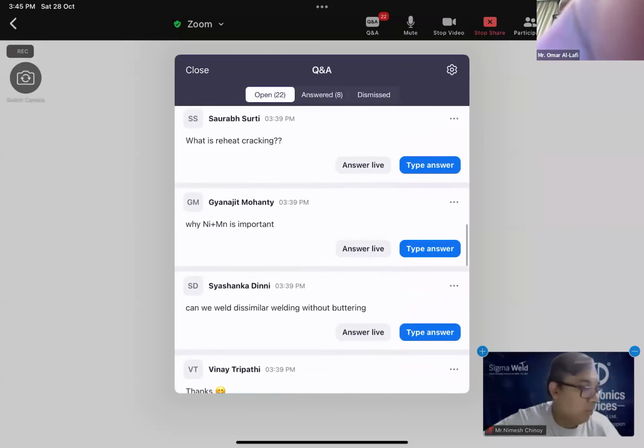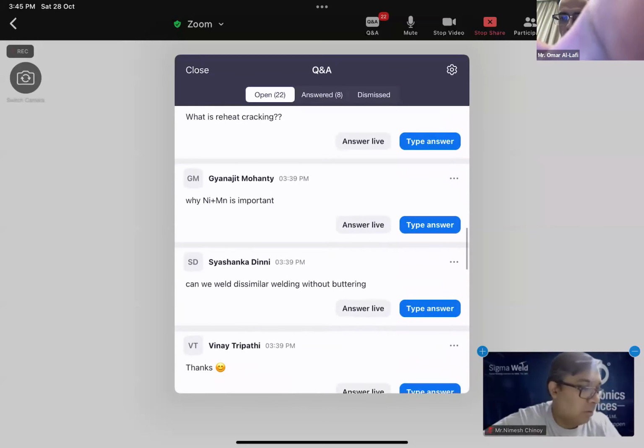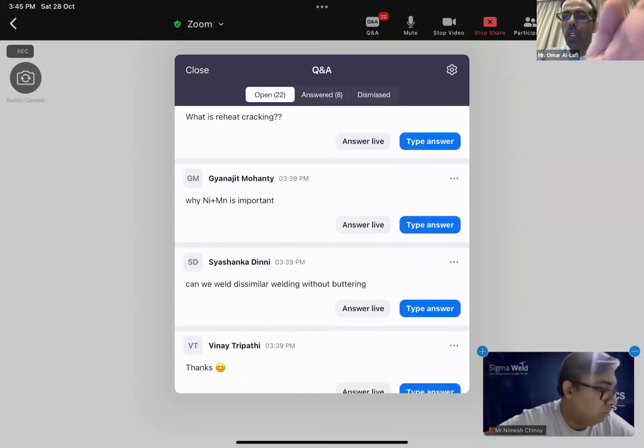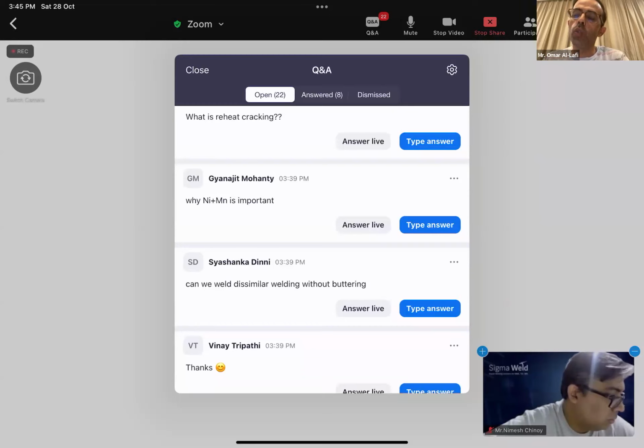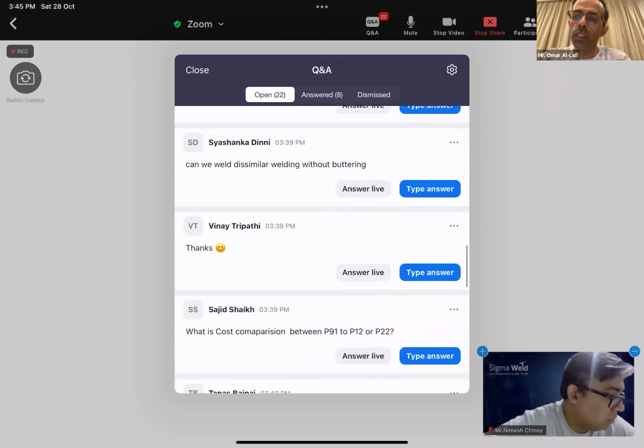Can we weld dissimilar weld without buttering? No, buttering is required, but the issue with buttering here is that it's difficult for testing. For example, we cannot rely on PAUT for testing the weld butter. So this is one of the common issues. But buttering is required when joining austenitic stainless steel to P91 material.